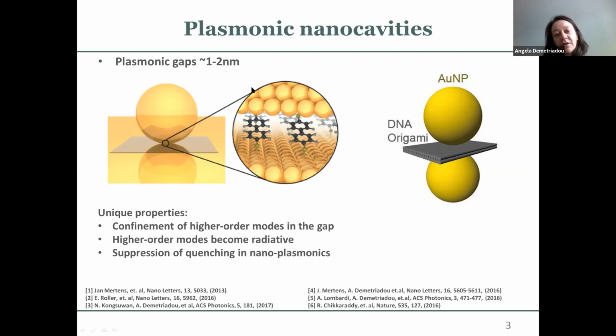You have a flat surface of gold. You assemble a molecular monolayer on top of it, where the molecule that you choose defines the height of your gap here, and then on top of the molecular monolayer, you assemble a gold nanoparticle, and you form this very well controlled gap here. This is the main method that the experimental group that I'm collaborating with uses.